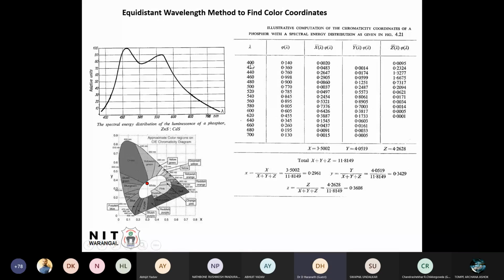At 400, this is the intensity value. Around 450, after 450, 460 or so, you have the peak. Here you see 460 is 0.998, and maybe at 461 or 462 it is 1. So this peak is normalized to 1, and all others will be lesser than that. Everything, the intensity values, is put here.